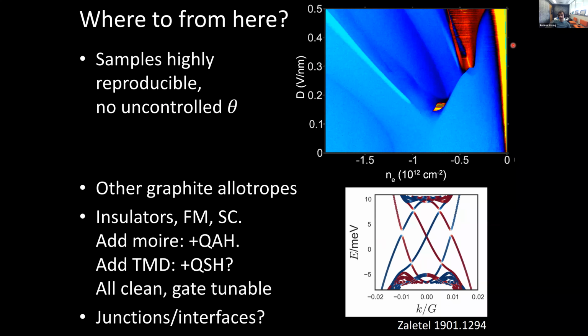We have not actually measured multiple samples to look for superconductivity, but when we've looked at density of states, the phase diagrams of these magnetic states seem to be identical from sample to sample, down to relatively quantitative questions of at what density and electric field does such and such a transition occur. It seems to be the same every time. So this means now you can kind of play with this. I think, of course, you can look at other graphite allotropes because this general behavior is generic to graphite, really. It wouldn't surprise me if it turns out that just regular graphite appropriately measured is also a superconductor of a similar type. But you can also couple it to a variety of other things.